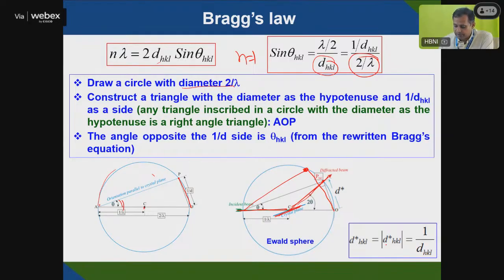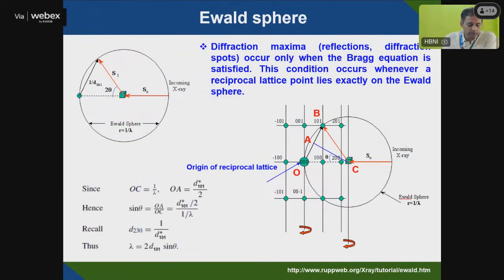So that modified dHKL, you can write this way. If you see here the Ewald sphere, as I told, S0 is the incident ray, and this is your diffracted S1, that's 1 by d. Then you can see this is the Ewald sphere circle, and this is the 101 lattice point, and it falls on this particular ring. Then you'll be able to see that particular 101 peak in the diffraction pattern. Since 201, 001 are not falling on this ring, you will not be able to see that diffraction plane.